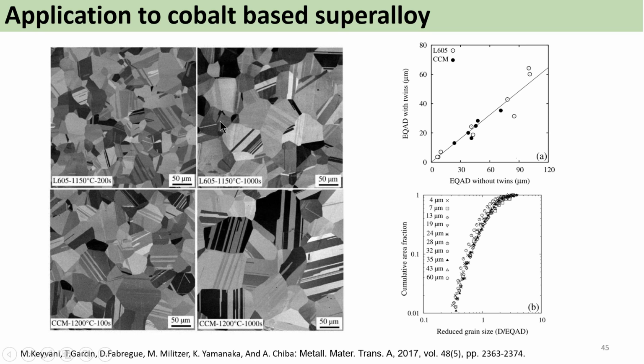And maybe I just want to make one note on those twins. These are considered as grains. That is to say, when we build a calibration we have to decide whether we measure the grain size including twins or excluding twins. Of course, this is the choice of the developer of the calibration, but we've chosen to consider twins as normal grains, as they have a discontinuity in crystallographic orientation, the same as between typical grain boundaries. Typical twins are considered as high-angle grain boundaries, so they should be considered as normal grains. We've developed this calibration, equivalent area diameter, including the twins.